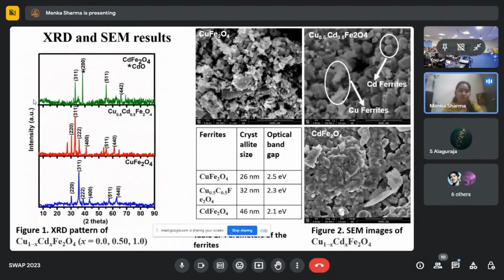So I have successfully synthesized cadmium substituted copper ferrite by the solution combustion method. These are the XRD results. From XRD, I have calculated the crystallite size. As we move from copper ferrite to cadmium ferrite, the crystallite size increases because of the lattice expansion. The morphology of the prepared samples was estimated from SEM. There is some agglomeration happening in copper ferrite as well as cadmium ferrite. The reason for agglomeration may be the magnetic nature of the sample.